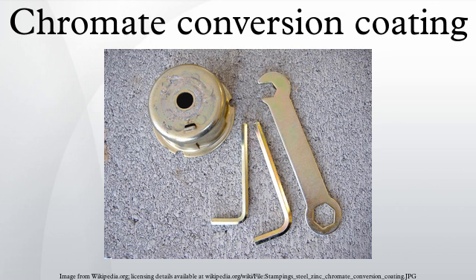Chromate coatings are soft and gelatinous when first applied, but harden and become hydrophobic as they age. Coating thickness varies from a few nanometers to a few micrometers. Curing can be accelerated by heating up to 78 degrees Celsius, but higher temperatures will gradually damage the coating. Some chromate conversion processes use brief degassing treatments at temperatures of up to 200 degrees Celsius, to prevent hydrogen embrittlement under the electro-deposited substrate underlying the chromate layer. It is typically specified for electroplated steels greater than 180 ksi tensile strength, and is normally performed prior to conversion coating. It is the pre-conversion plating that requires embrittlement relief, not the chromate conversion coating itself.